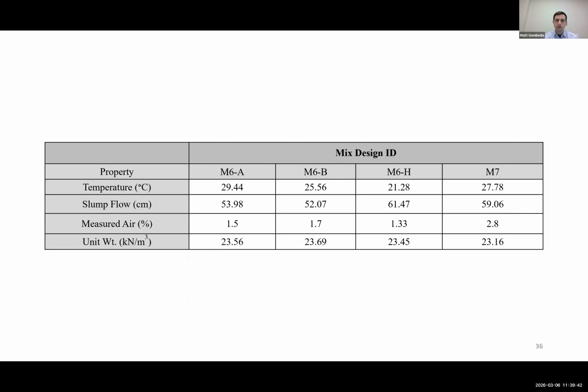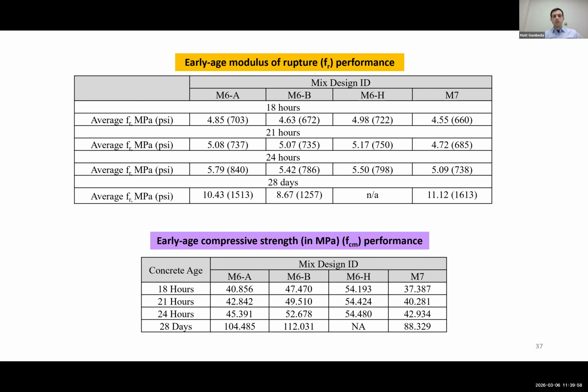Here are some workability properties that we measured from the testing that we did. All of the slump flow targets were to get SCC performance, so we're at or above a 20-inch slump flow in each of those cases, which was satisfactory for us. And then we look at the early age modulus of rupture performance. Our target was, again, 750 at 18 hours. We got pretty close. It wasn't easy, but we were able to get 722 in the heat mix, and we were able to get over 700 in the first M6 mix.